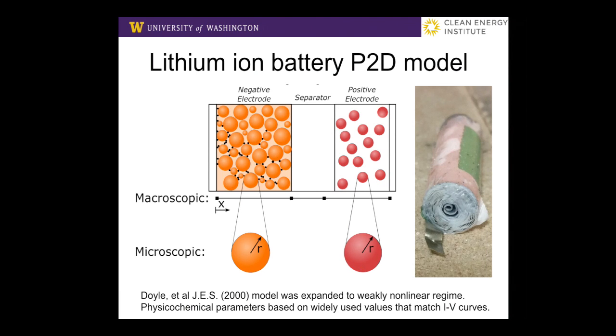Okay, and so we have a porous electrode. That's the negative electrode will be a carbon electrode. The positive electrode on that side will be, for this case, lithium cobalt oxide, one of the high energy density batteries, the one that burned in the Boeing plane. In the middle is a separator, which is a porous polymer that tries to keep it from short circuiting, but allows ionic transport through the middle of it.